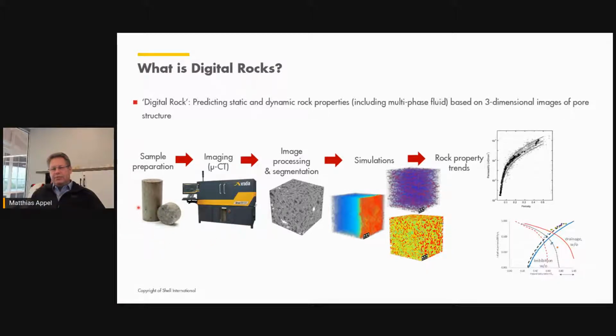The workflow that has been developed in the industry, and that is not specific for Shell here, is something called digital rock. It comes in different names for different companies or integrated service providers, but roughly it's always the same. You take a sample, you need to prepare the sample in terms of identifying the heterogeneities roughly, and we are talking about that a little later. You take mini plugs from these samples, millimeter-sized mini plugs, and you do the high-resolution micro CT imaging. These images, these are 3-dimensional volumes of images, are then processed. Typically, you need filtering. You definitely need some cropping. You can't work with the entire image mostly. You need some segmentation.